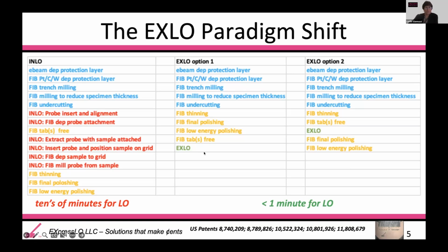So the general steps for FIB specimen preparation for in situ lift out and for ex situ lift out are essentially identical, with the only differences being how you get the specimen itself to a suitable grid carrier. And it is well known, there's no secret here, that it can take several minutes, up to tens of minutes, up to hours for some users to do in situ lift out, compared to less than a minute or just a couple of minutes for ex situ lift out. And so the speed is not disputed.